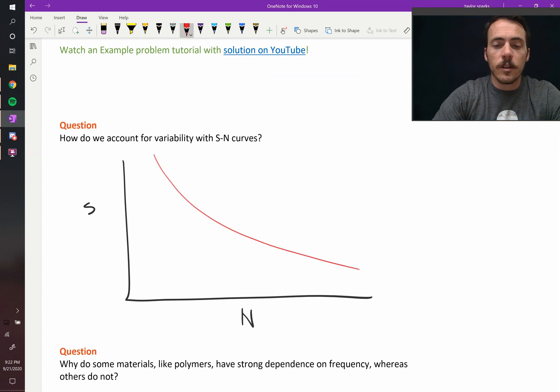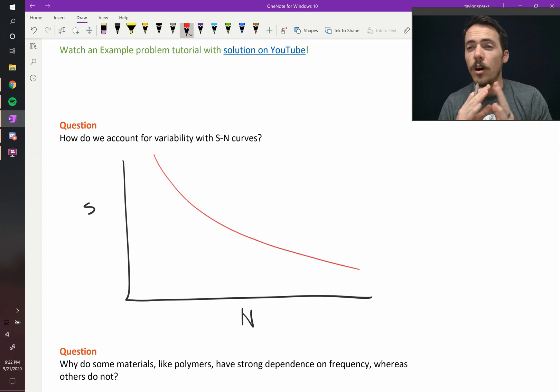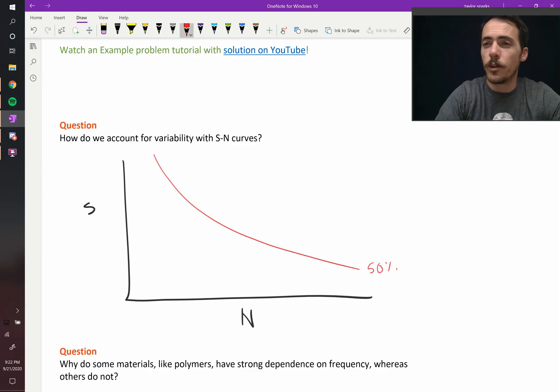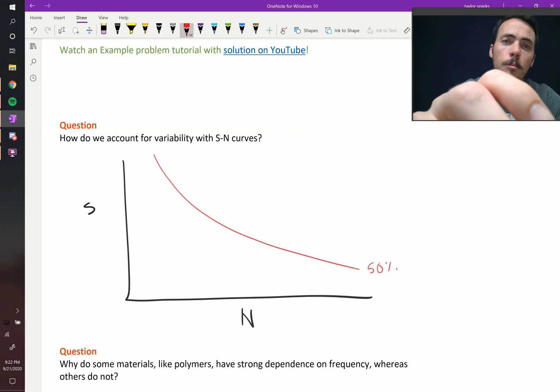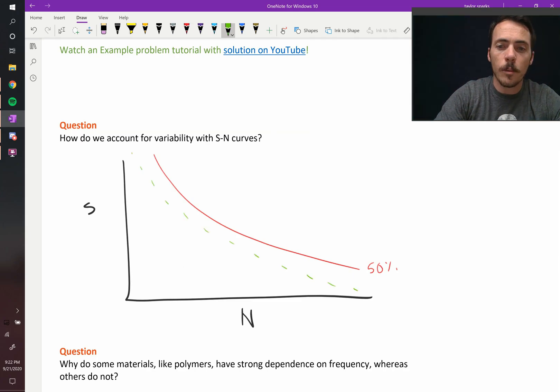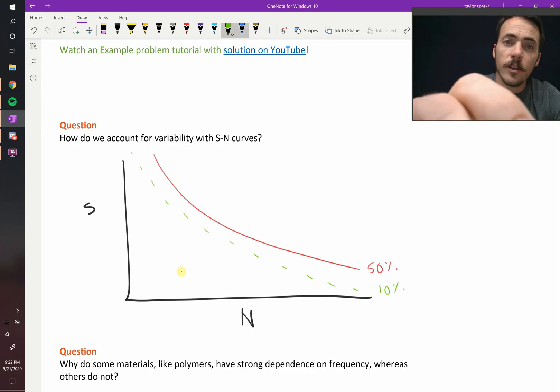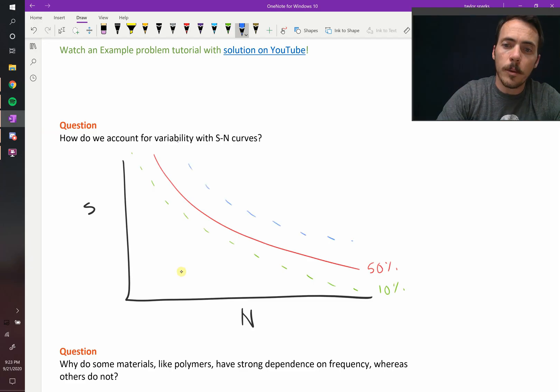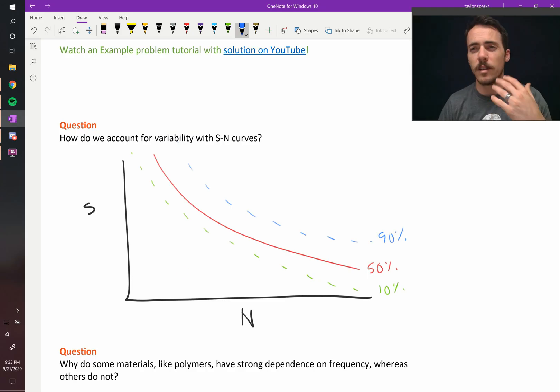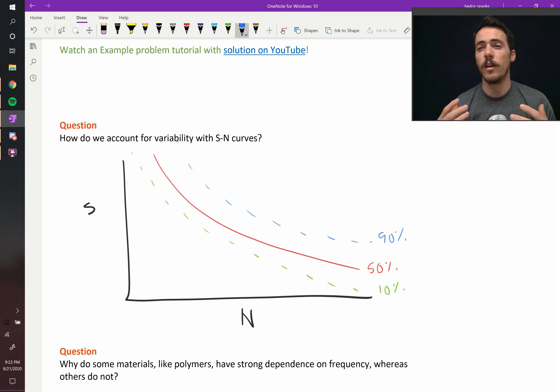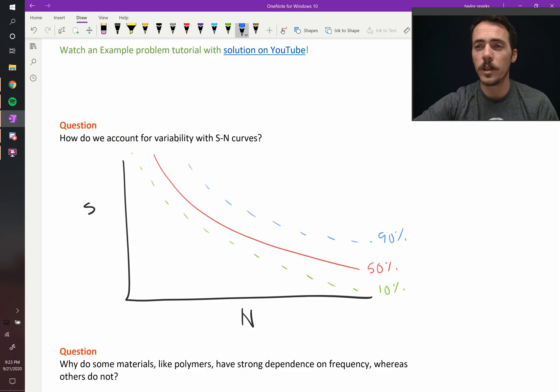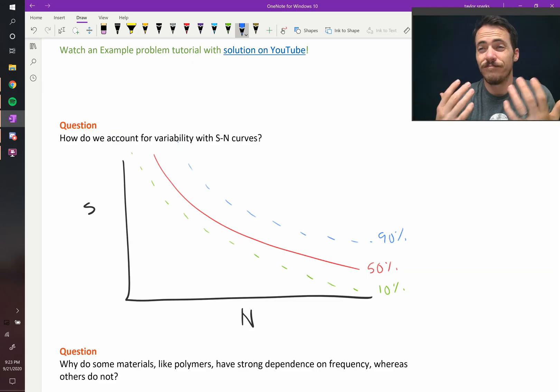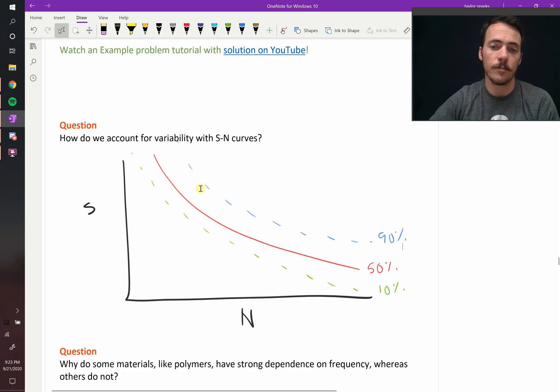What they'll often show is just the curve. Let's say your material looks like this. But that's if you averaged all of your samples. So this is maybe the 50% failure rate. On average, that's how your materials behave. But it would be equally, maybe even more useful to show a curve right here, which represents when 10% of your samples will fail. And then show another curve where maybe 90% of your samples fail. So adding these lines that take into account the probability of failure is much more useful than a single average value. We're going to talk about variability in data a little bit later when we talk about Weibull statistics, but it's a really useful tool for thinking about materials as they actually are, which is not homogeneous. There's variability in this. It's taken into account for it.